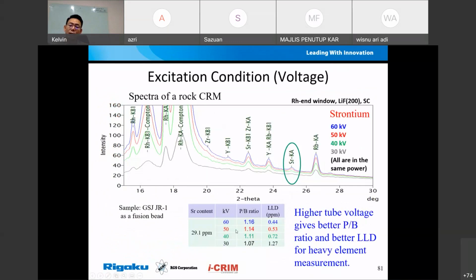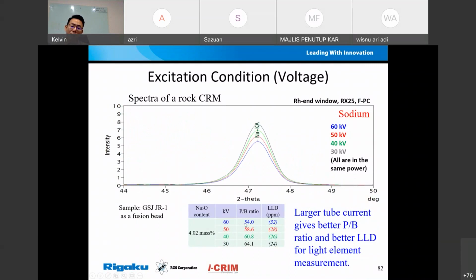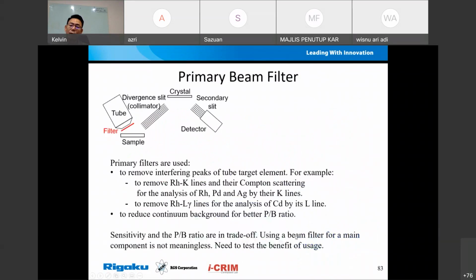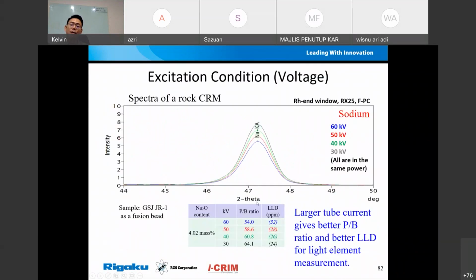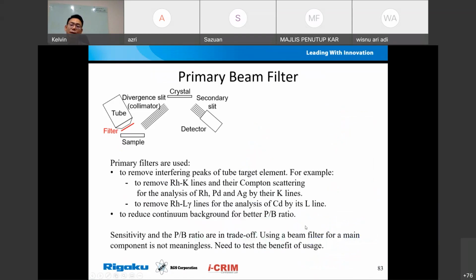As you can see in here, this SR is 29 ppm. Increasing the kV doesn't change too much. Like from this one, the P/B ratio is 1.07, and going all the way up to 60 kV, it only increases a little bit. This is also the voltage. So it just means it doesn't improve much in terms of the voltage. The intensity doesn't increase much with the voltage.